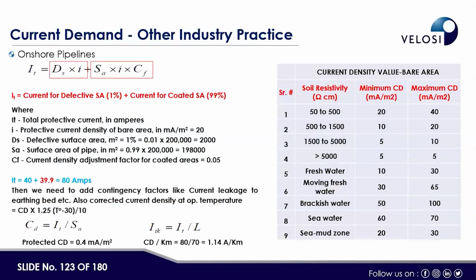So this is the current demand calculation. Another method to calculate is by the bare metal surface area. For bare metal exposed in soil with resistivity varying from 50 to 500, as in a coastal area, your bare surface area requires 20 milliamp per square meter and maximum 40 milliamp per square meter. So this is a different way to calculate the current requirement of the pipelines.